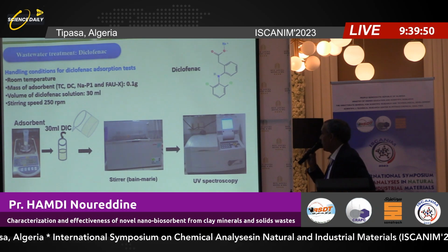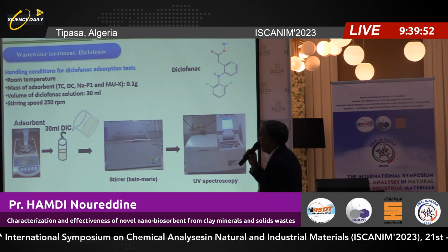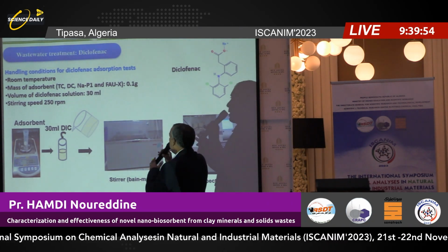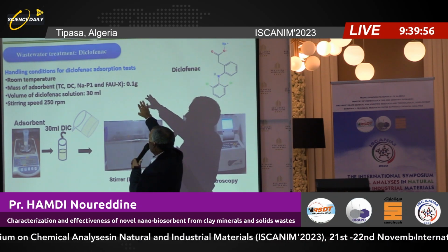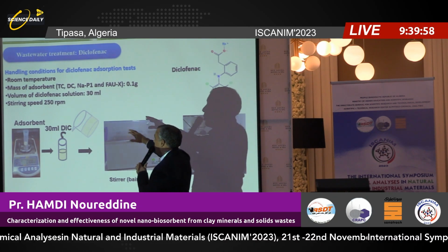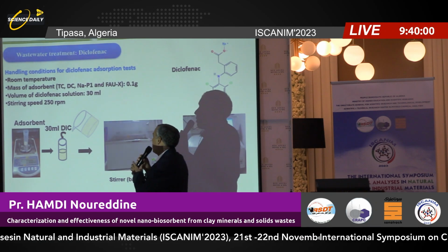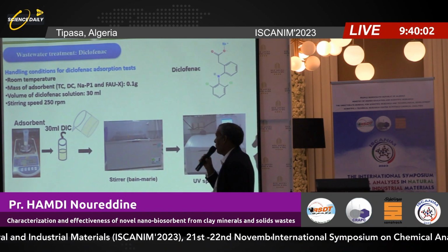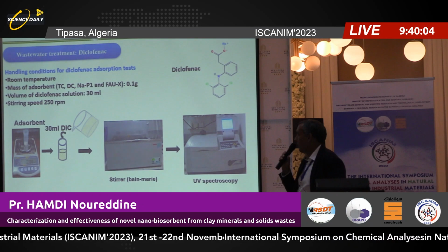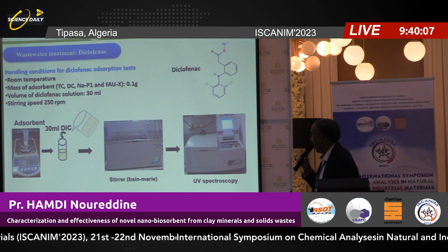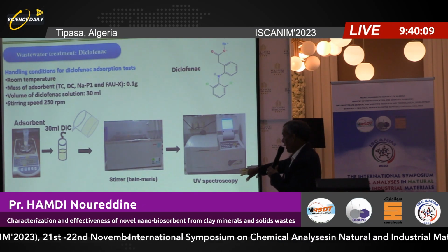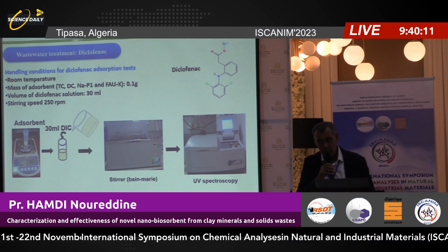And in the experimental study, the mass of the adsorbent is about 0.1 gram, the volume of the diclofenac solution is 30 milliliters, and the speed is 250 rotations per minute, and the analysis is done by UV spectroscopy.